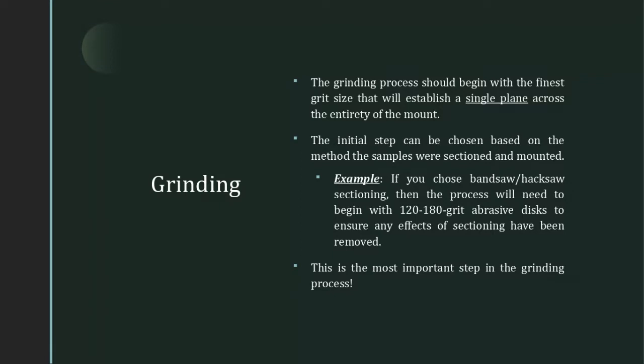During the grinding process, the best way to start once again depends on how you section your sample. You're going to start with the finest grit size possible that can establish a single plane across the entirety of the mount. So if you started off with a hacksaw or bandsaw, chances are you'll need to start with 120 or 180 grit in order to get your entire sample on one plane, removing the effects of the disturbed metal caused by that particular sectioning process.